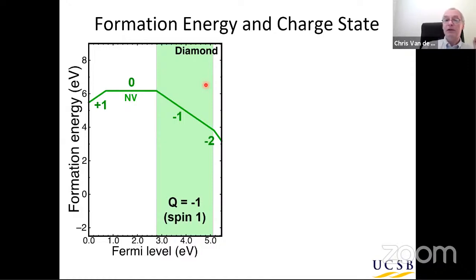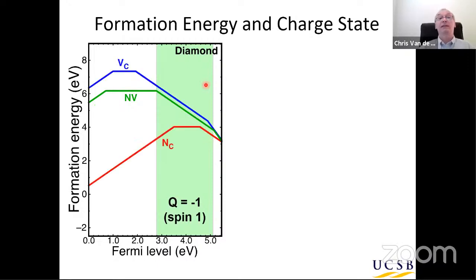In the case of the NV center in diamond, we are actually lucky. Maybe this is actually one of the reasons for the success of this center. Because if you look at other centers or impurities that are commonly occurring in diamond, well, you can look at vacancies, but actually, even in natural diamond, nitrogen is present in fairly large concentrations as an impurity. And of course, that's also why you have these nitrogen vacancy centers.